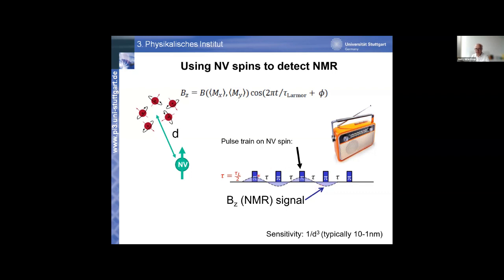And because we can change tau quite easily, technically, we can actually scan across a certain frequency range and pick up the magnetic field specifically at that frequency range. And that's how we do it. So essentially what we measure is a magnetic field component, say, along BZ, which is modulated with the Larmor frequency of the specimen or of the nuclear species we are interested in.